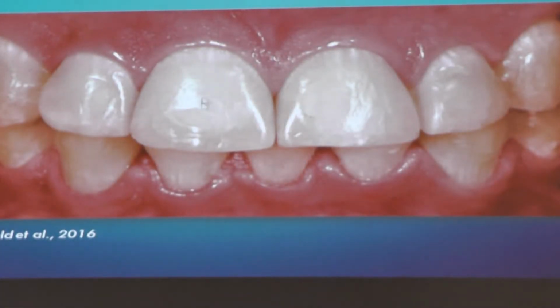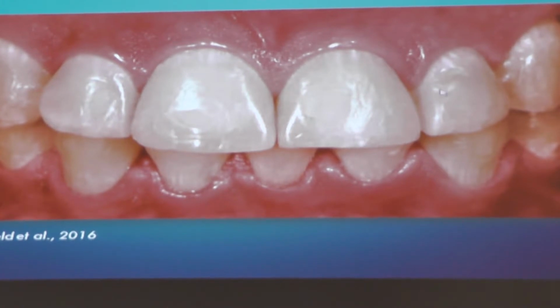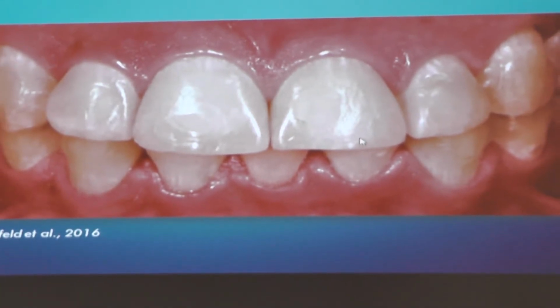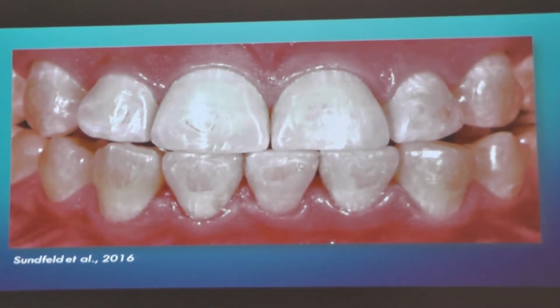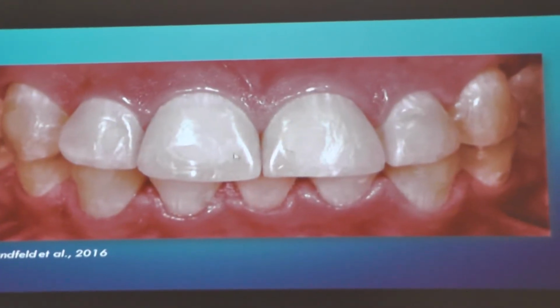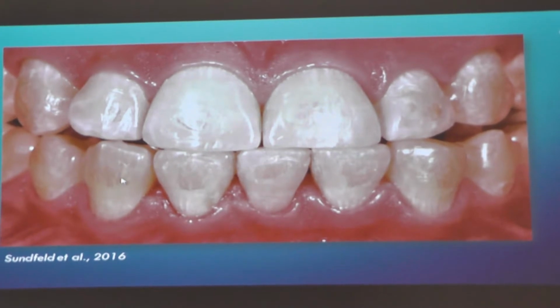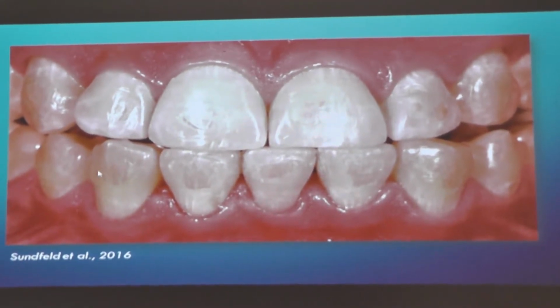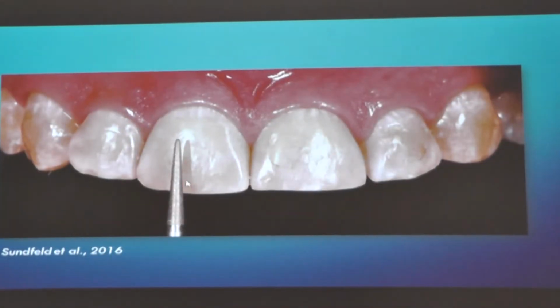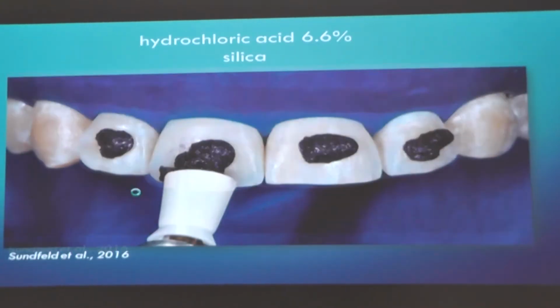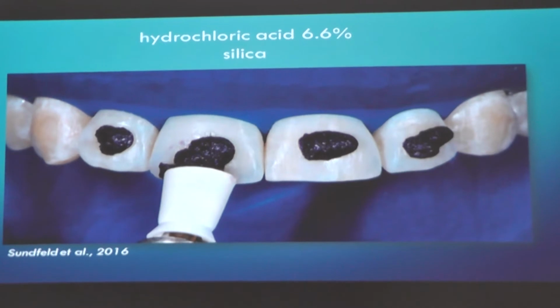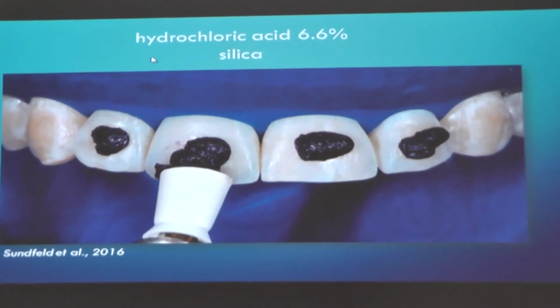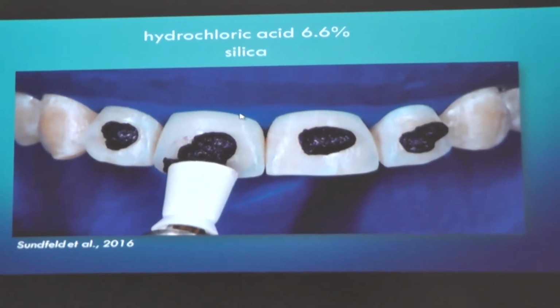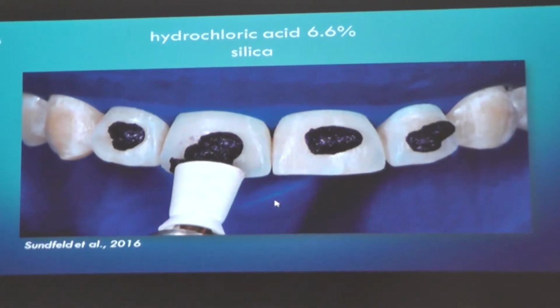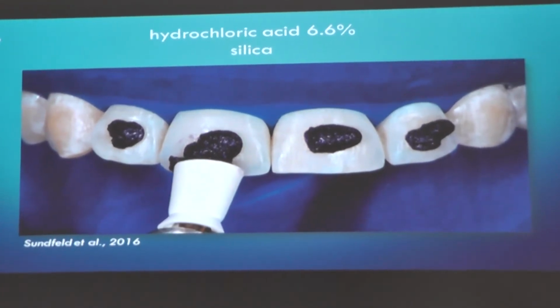And so if we have to use primer, how do we deal with the remaining bonding material, the remaining adhesive? This is a clinical case that they showed. From this you cannot see it, but it is the same patient at the same moment. It's just that they scratched the labial surface with the probe so that you can see these gray areas. This is the bonding material, and then they removed it with the tapered fine diamond burr, and actually used microabrasion. It is a paste that contains hydrochloric acid for whitening, and very fine silica particles. So they actually remove a very thin superficial layer of enamel that is about 25 micrometers thick.